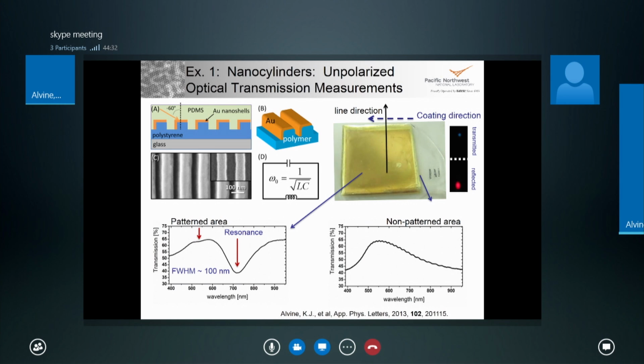This first slide talks about the nano cylinders that we're making. Again, these are actually gold - we're using gold as a surrogate material. Typically for window films you'd want to use silver or aluminum. So we make these simple line space gratings, made with imprint lithography, and then we coated them from 45 degrees with the gold to make these nano cylinders. These structures show a dichroic response.